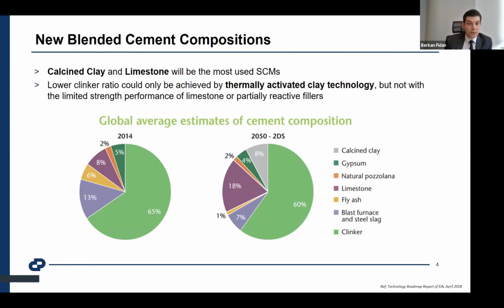At that point, the last option is limestone and the other fillers, but these are not as reactive as the others. They just work as a filler with a very tiny effect on clinker strength and other issues. Then we need an additional material, and it should be abundantly available all over the world. At that point, calcined clay becomes a potential option, and a lower clinker ratio could be achieved with that thermally activated clay composition. It also has a higher effect on strength compared with limestone and the other filler components.